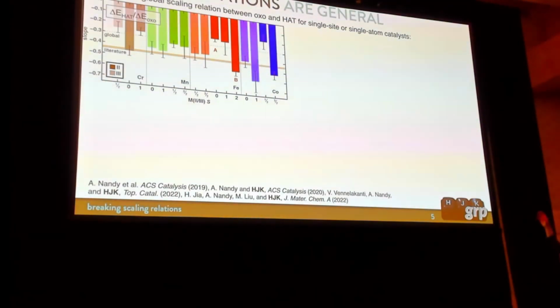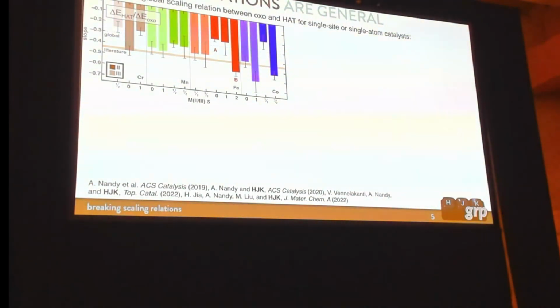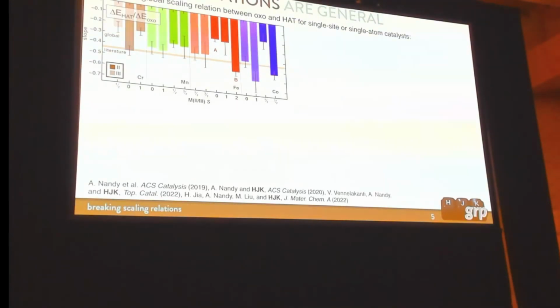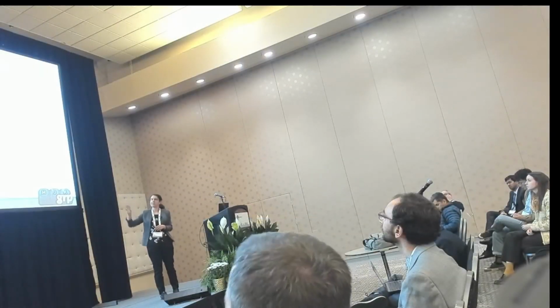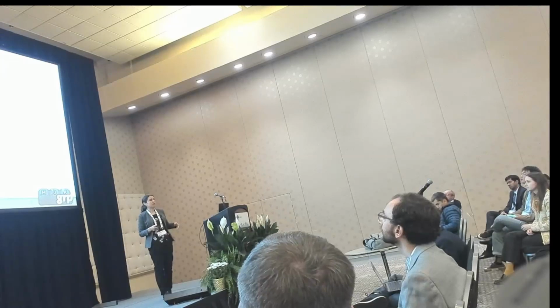And you can see here the error bars are the standard error of a fit linear free energy relationship just on the individual metals. The tan line there is the literature value typically recorded for the hydroxylation versus oxo-transfer trade-off. The global fit is what it is over the whole set, and you can see that the global linear free energy relationship just doesn't apply in comparison to the individualized scaling relations. So even if we wanted to use a scaling relation, we have to use the metal and oxidation state to have a match. So this was work done by Uschi Graham, who recently graduated and will be starting at UCLA in chemical engineering in a couple of years.